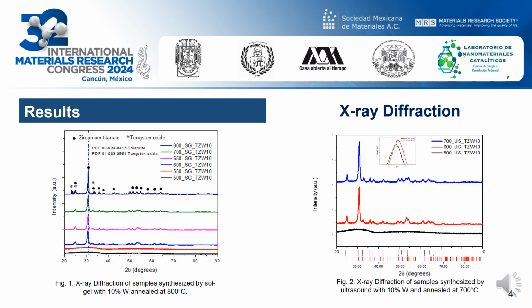From X-ray diffraction, it was found that for both series annealed at 500 degrees, the patterns are characteristic of amorphous materials with an induced phase near 30 2-theta degrees corresponding to the 1-1 plane. After raising the annealing temperature, it was observed that crystallization began at 550 degrees. When the temperature was increased to 800 degrees, the appearance of srilankite was observed, as well as a tungsten trioxide segregated phase. Another effect detected was that when the tungsten content is increased, the stability improves, and the presence of tungsten trioxide is associated with the formation of tungsten oxide-zirconium bonds on the surface of the material, which reduce the mobility of the zirconium atoms on the surface, preventing sintering.